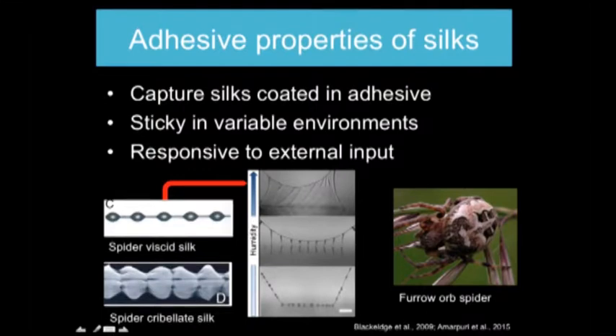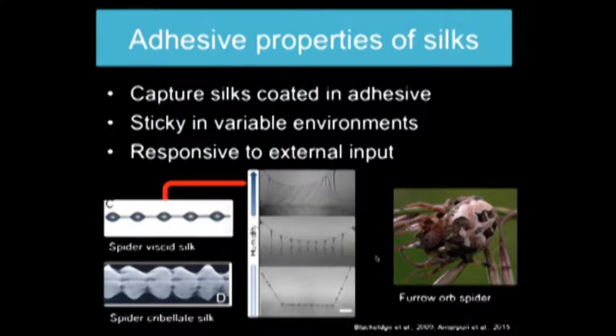In dry conditions, in some species, the droplets stick directly to substrates and don't necessarily deform very much. At increasing humidity, they become more and more liquefied and then deform at greater levels. It's really something quite remarkable, and there are many studies recently that have been done that exemplify this.